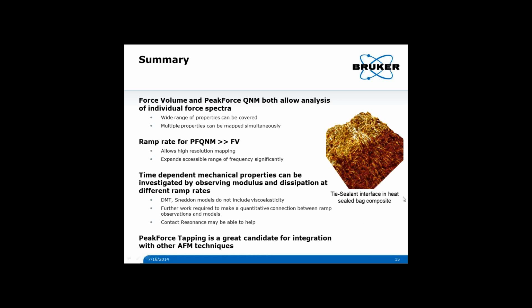topography is not enough. This is another view of that interface where we were not even able to see the interface at all from the height map, but the modulus gives us an exact position of it. And PeakForce QNM has the speed to allow acquisition of high-resolution property maps in a reasonable amount of time, while force volume allows comparison to slower ramp rates. Together, these two techniques allow a wide range of ramp rates needed to study the time-dependent effects.